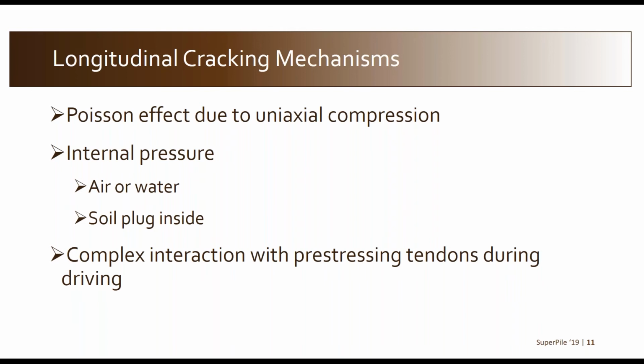This last one is kind of a catch-all, actually, for a number of mechanisms. The fact that you're driving this pile and it's a dynamic situation means that everything about it is complex in terms of the mechanics. One aspect of that is that as the compressive stress wave travels down, the pile shortens slightly because it's in compression. And if you take a pre-stressing strand that's locked off under tension and you shorten it a little bit, it's effectively relaxing. So the load drops off. So that further changes the stress distribution, at least locally, in the pile as that stress wave is traveling down.